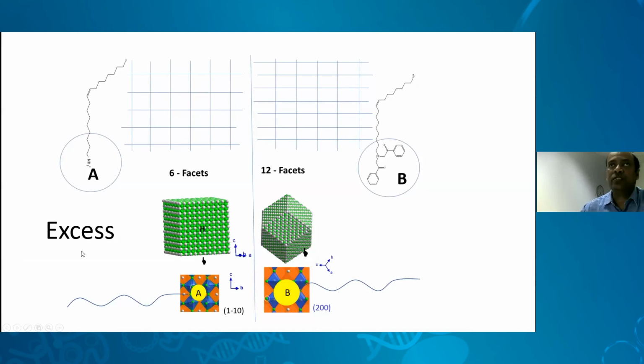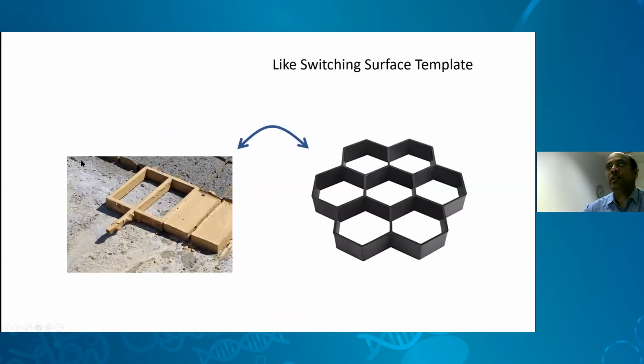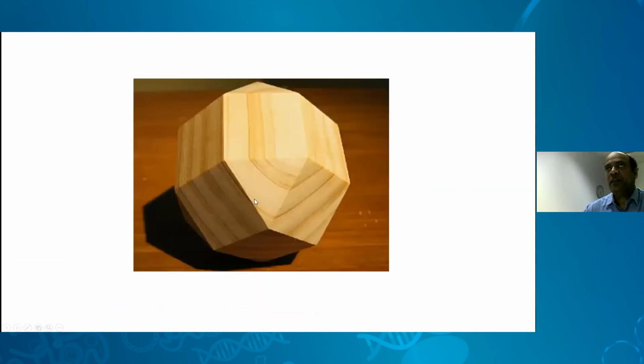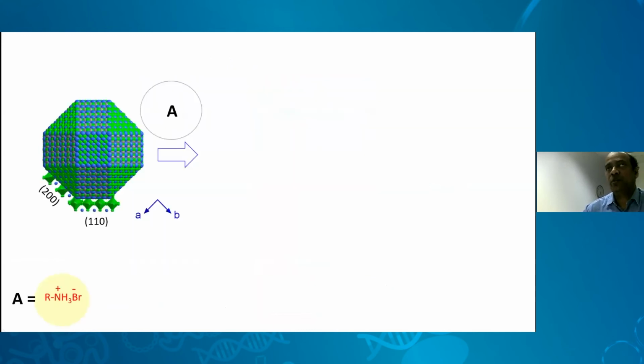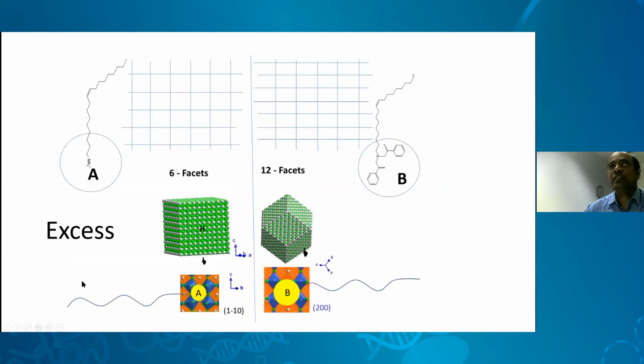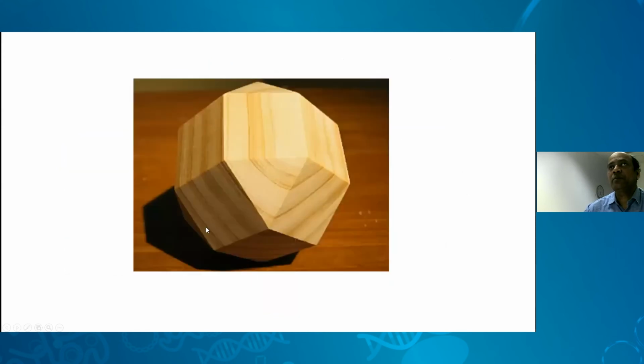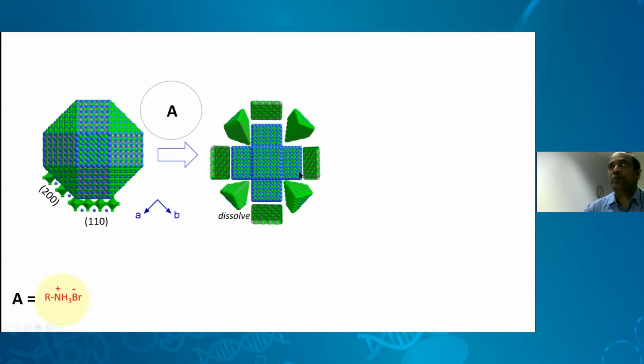This is a more amazing structure, we'll see it out, like in switching between the two facets here. Take these structures, formed either from the cube or from the dodecahedron. We took this one and we treated it with excess of A. A is the primary ammonium bromide in chemistry terms. As I was talking about, this A is only capping or stabilizing this particular facet. When we put A on this, we found that apart from the center, all those new facets created are dissolved out.